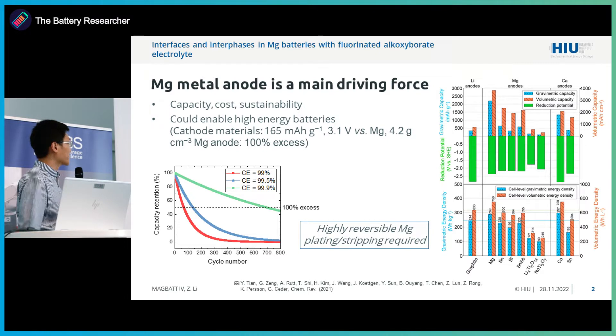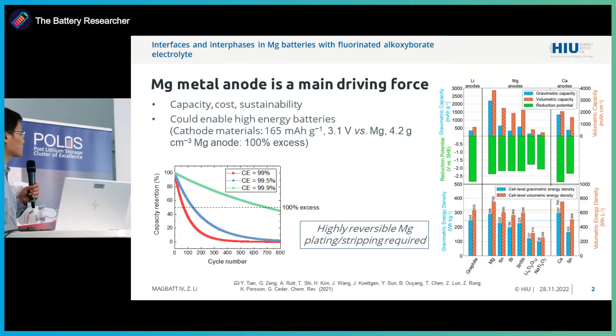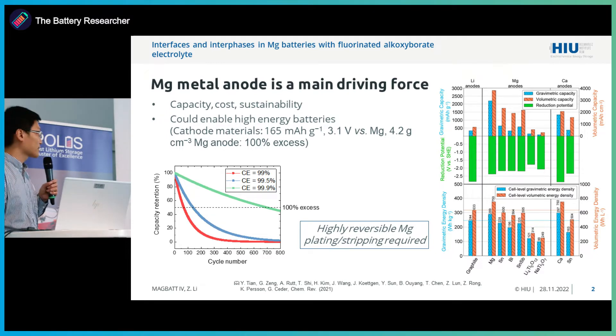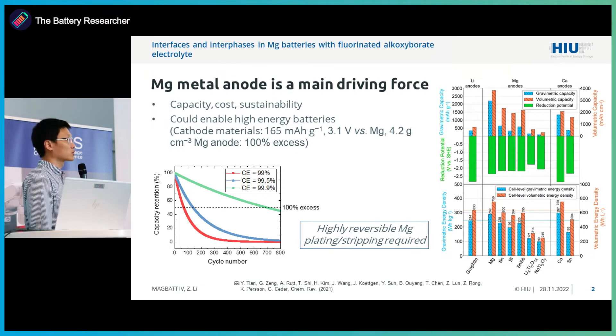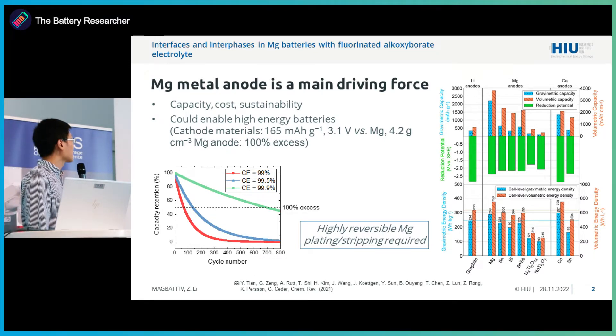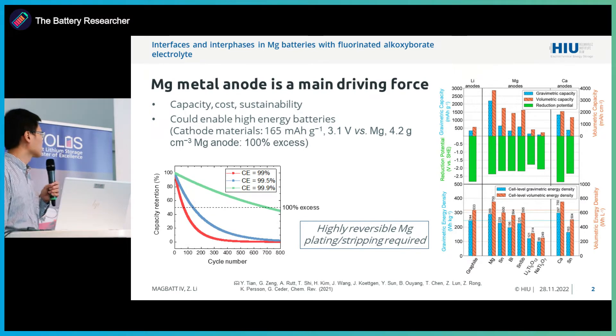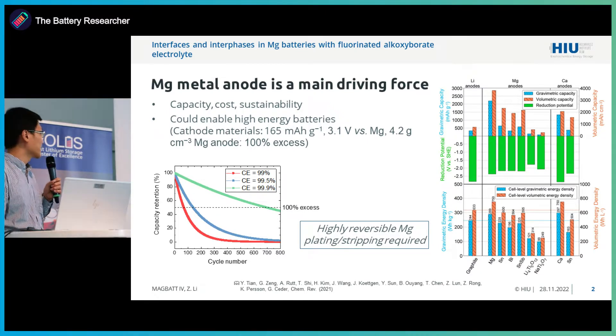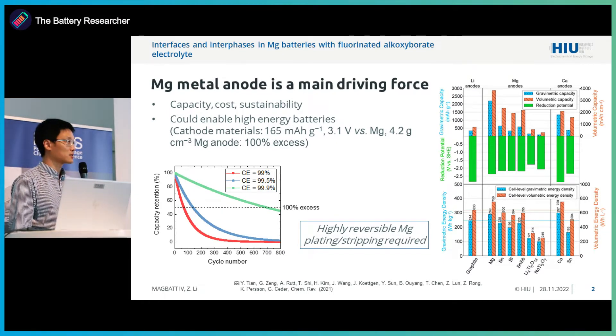Of course, this estimation is based on the assumption that we have a well-performing cathode that delivers a capacity of 165 mAh per gram at 3.1 V versus magnesium. But on the other hand, if we want to cycle the cell at full capacity, we also need reversible magnesium plating, as also mentioned by Doron.